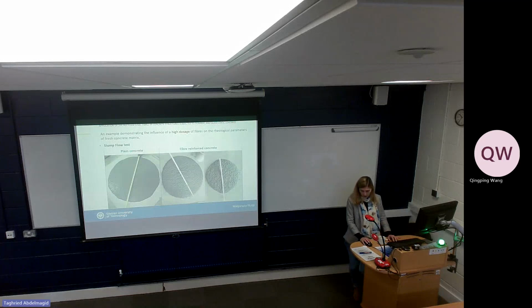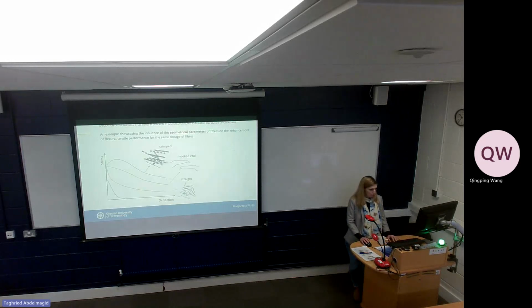And now the second part, we have the slump flow tests. And when you add the fibers, it highly decreases. So again, this kind of concrete cannot be poured everywhere because it just won't work. So the reduction of flowing ability, of course, is connected with the high dosage of fibers.